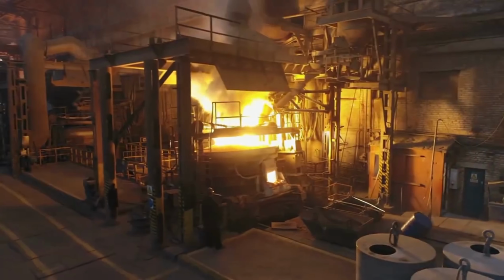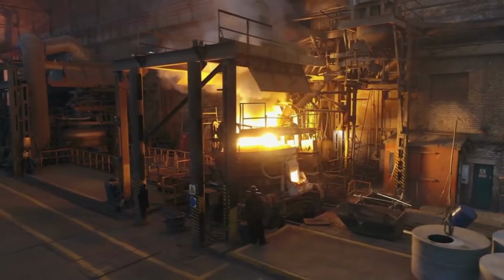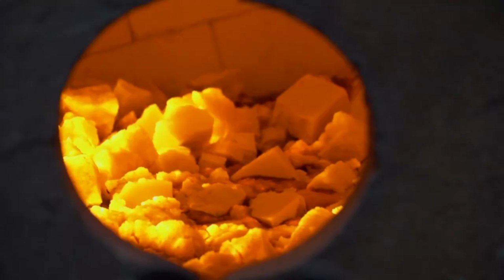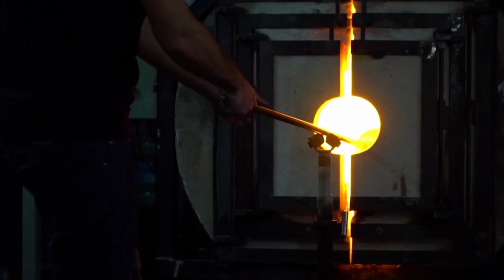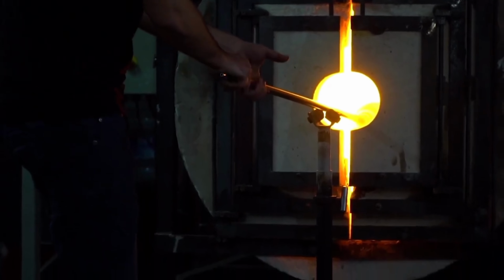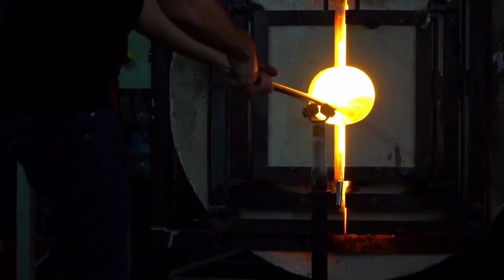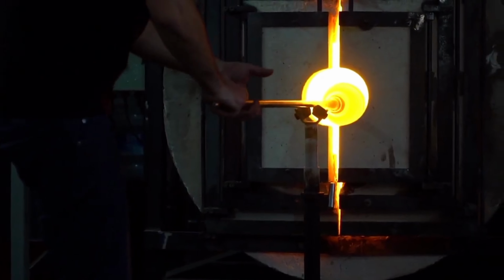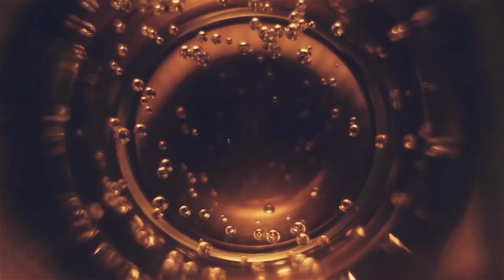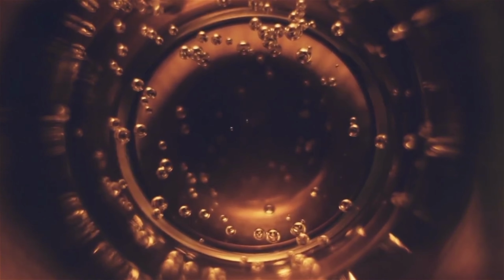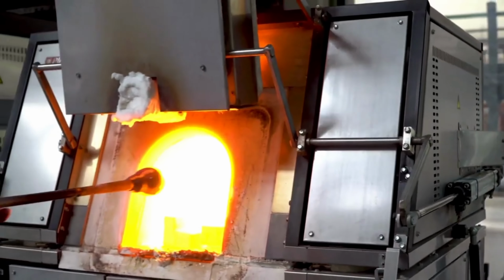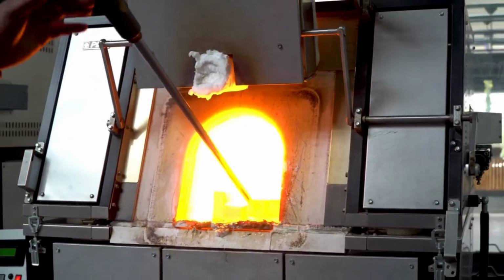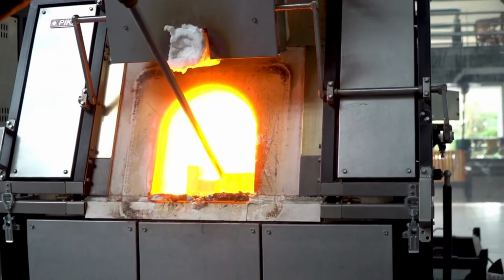A massive cathedral of fire constructed from refractory brick and engineered to run continuously for years at temperatures exceeding 1,500 degrees Celsius. Where inside the inferno, the batch transforms from powders to glowing molten orange liquid glass, resembling thick honey made of light. And as the mixture melts, heavy impurities sink, bubbles rise, and mechanical stirrers ensure the molten mass becomes crystal clear and perfectly uniform, because even microscopic variations could weaken the finished bottle.